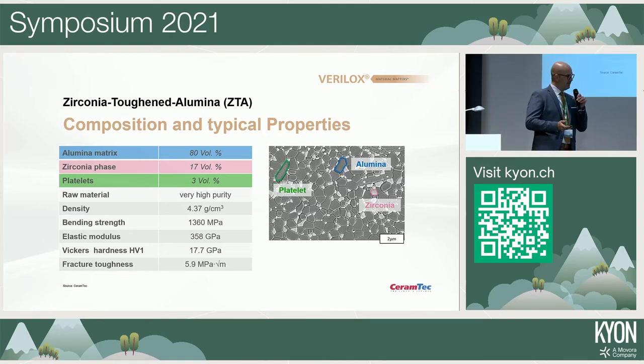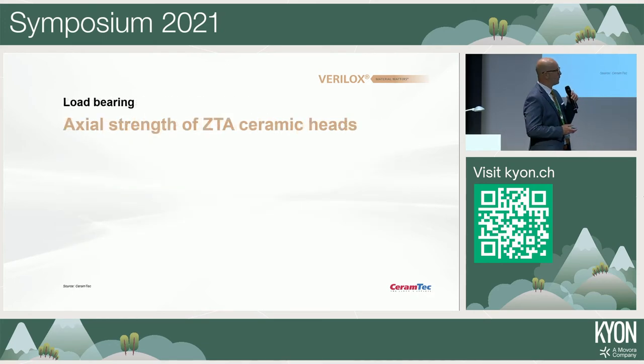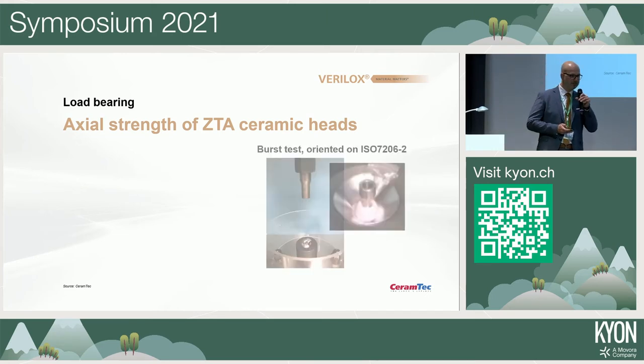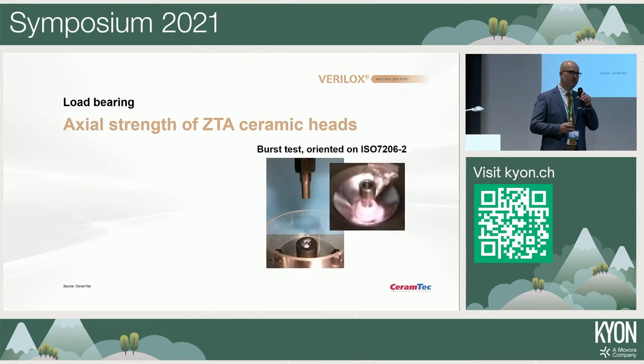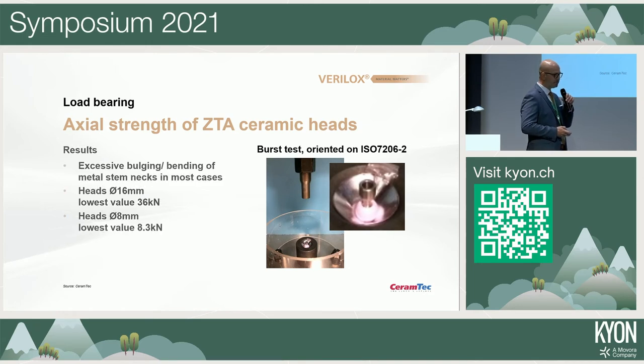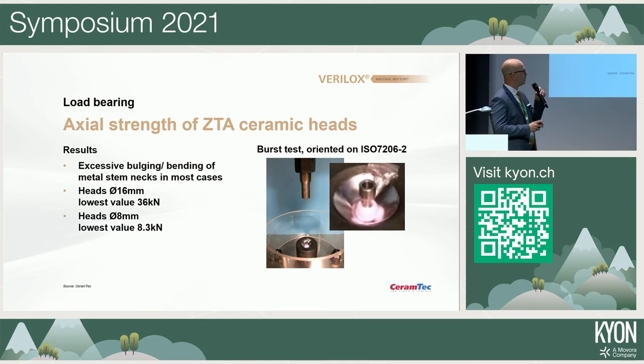Since I mentioned the surface preparation plays a role, it makes also sense to test the finally manufactured component. And we do this with a bunch of tests which were developed for the different kind of implants. And for the hip implants, the test of choice is the axial burst test. And we also did this with the small heads for the veterinary application. And what we saw there, we did the test not completely in accordance, but oriented on the ISO standard for the hip implants in humans.